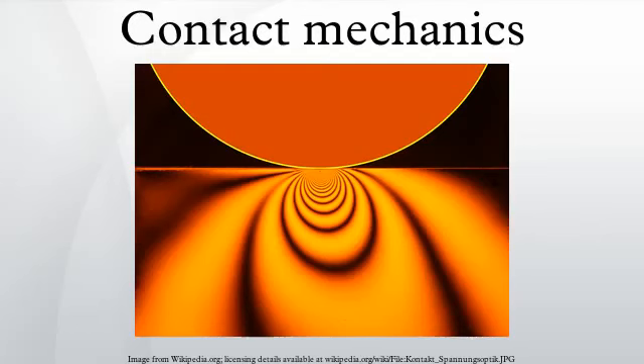This rejection proved to be instrumental in the development of the Tabor and later Maugis parameters that quantify which contact model represents adhesive contact better for specific materials. Further advancement in the field of contact mechanics in the mid-20th century may be attributed to names such as Bowden and Tabor. Bowden and Tabor were the first to emphasize the importance of surface roughness for bodies in contact. Through investigation of the surface roughness, the true contact area between friction partners is found to be less than the apparent contact area. Such understanding also drastically changed the direction of undertakings in tribology.